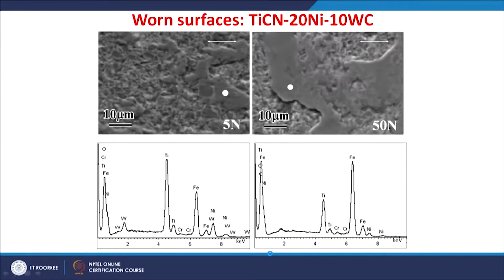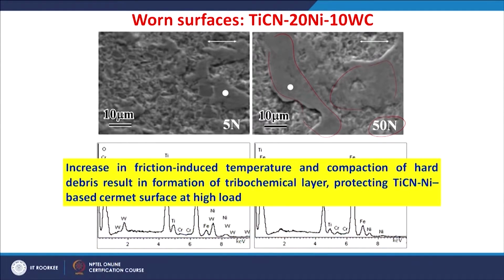The worn surfaces of the titanium carbonitride nickel tungsten carbide cermet show again, at lower load, minimal presence of this layer, whereas at higher load you will see the majority of the surface is covered by this layer. And again the EDS analysis shows a similar observation, that they become richer in iron oxide at the higher load conditions.